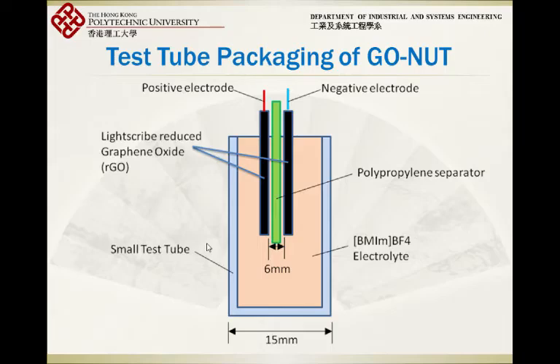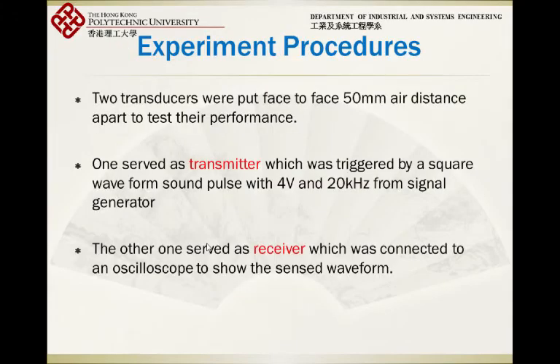That is ionic liquid. So why do we use ionic liquid? It's because it can give a higher potential window. So we can apply higher voltage, like 4 volts or 6 volts. But of course, we can also use water-based electrolytes, like acid or base, which can only give as high as 1 volt of bias. And this is just a test tube, and this is the packaging of the device. And I would like to show you the testing procedures. So we only apply 4 volts, 20 kilohertz. You use a square wave to trigger the device.